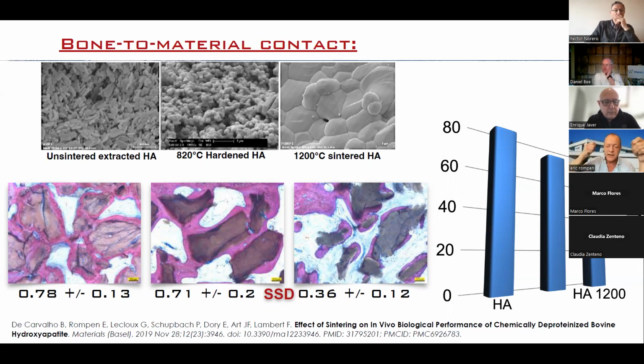So that means that when we drill the regenerated area with a material that has a low bone to material contact, you will obtain a very soft bone. When with a very high bone to material contact, the regenerated tissue will be very dense, which is of course very good for the primary stability of our implants. And that has been published quite recently in Materials by our team.